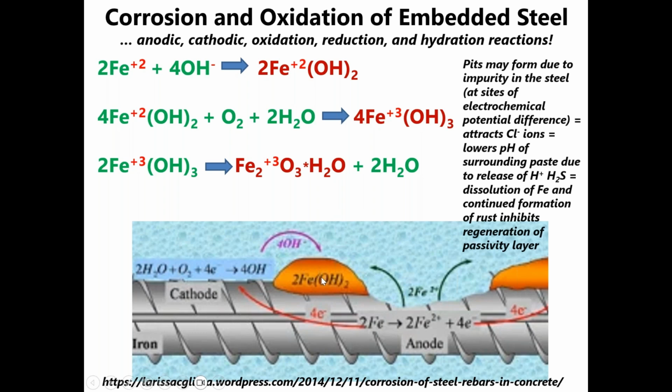And pretty soon the formation of rust chokes out the ability of the passivity layer to rejuvenate itself, and the pits and corrosion that are affecting the steel just become more and more pronounced, and the steel is dissolving away, but reprecipitating as this rust, quote unquote, elsewhere.